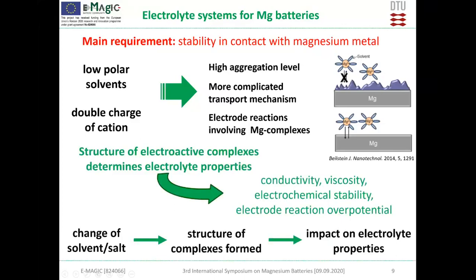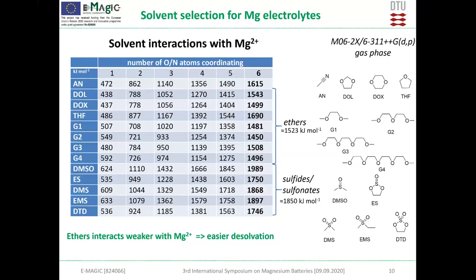So indeed, at DTU, we are trying also to suggest some other solvent or change of the salt. At the beginning, going to the solvent, we did just simple screening, just looking at interaction energy in the vacuum between magnesium and different solvents, different groups of solvents. And what we noticed is that from the solvents that we screened, only ethers provide a middle strength of interaction. So only these solvents will provide easier desolvation. So we went into more detail on the glymes.